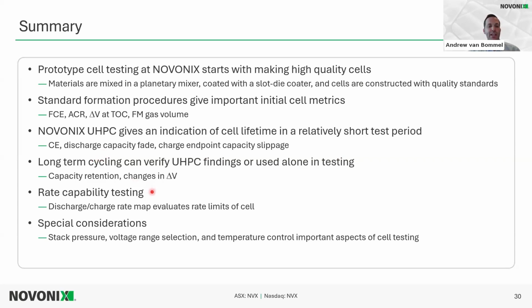And then we use rate capability testing. This is interesting if you are looking at testing different conductors, different compression densities, different formulations. It's great to test that to evaluate the kinetics of your cell. And this is done through that discharge and charge rate map, which is a destructive test, and it evaluates the rate limits of that cell.